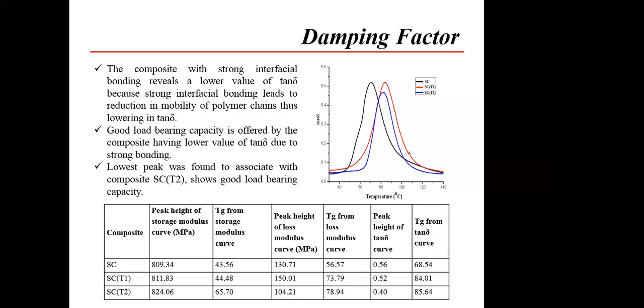After going above this temperature, the material changes its state from the glassy state to the rubbery state and becomes softer. So this is not applicable above 56 degrees Celsius. In case of SCT2, we can use it up to 78 degrees Celsius.